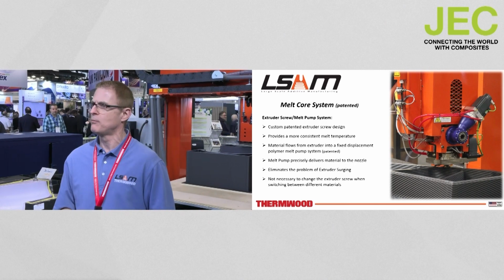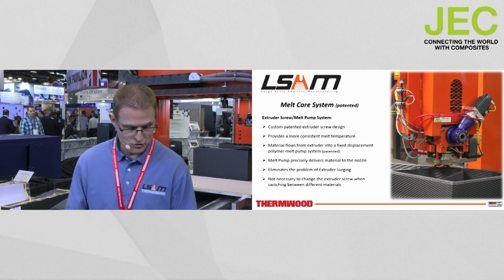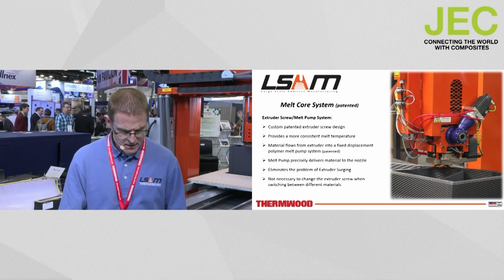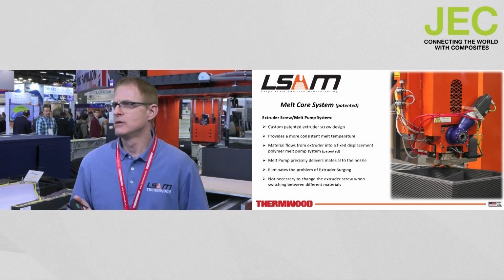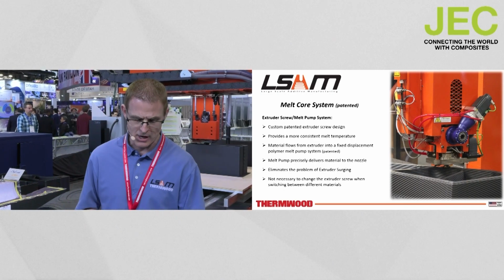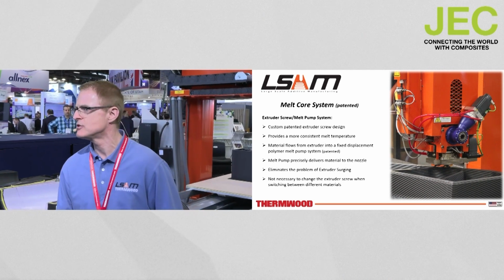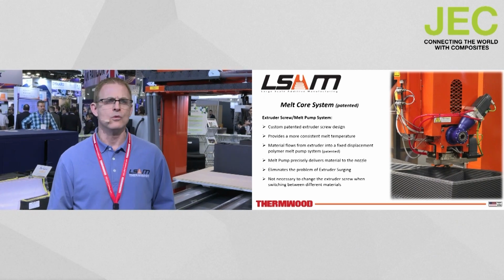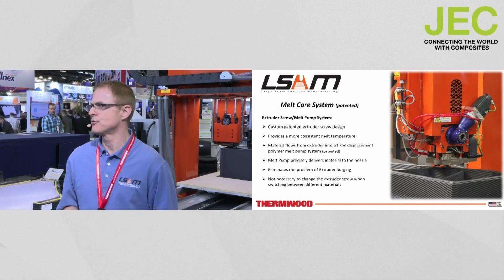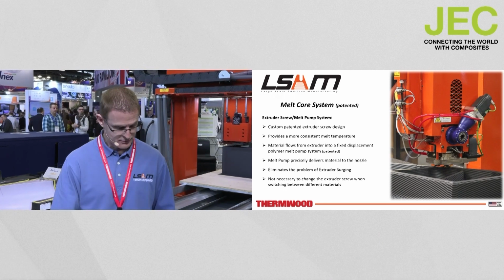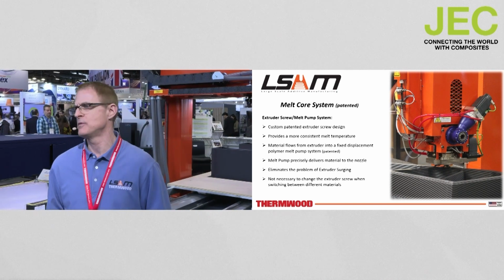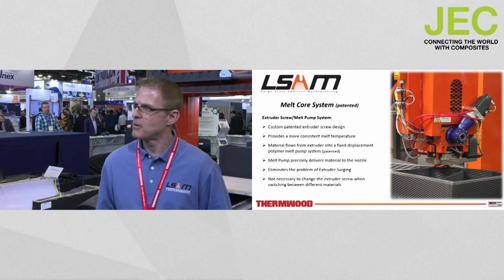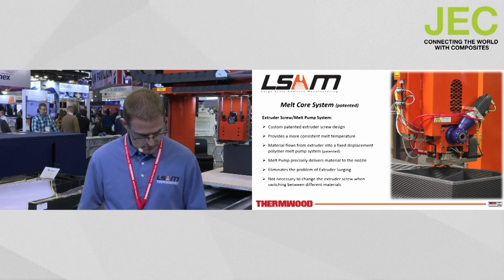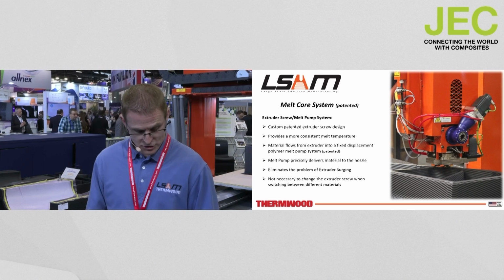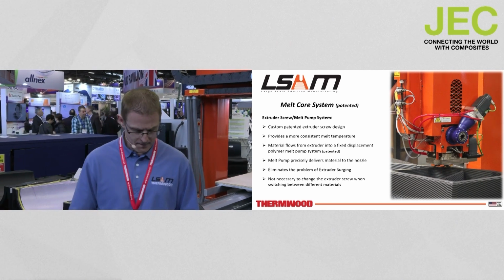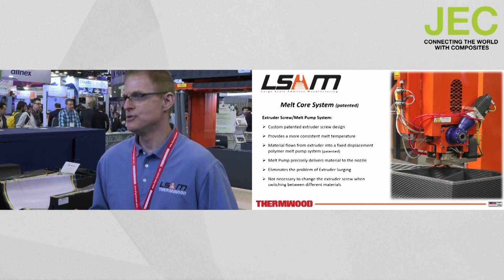First, the melt core's extruder screw and melt pump system work in complete unison to provide the most accurate and precise material output possible. In large-scale 3D printing, the extruder screw must change speeds constantly, or RPMs. So this custom patented screw design provides a more consistent melt temperature across these ever-changing speeds. Also, it is known that an extruder alone will not produce a consistent material output due to extruder surging. This is especially a problem at high output rates. So our extruder's only job is to keep a positive displacement melt pump system fed, and then the servo-controlled melt pump precisely delivers material to the nozzle. This eliminates the problem of extruder surging and produces the most accurate and consistent material output possible. And an added note, it is not necessary to change our extruder screw just to change to a different material.